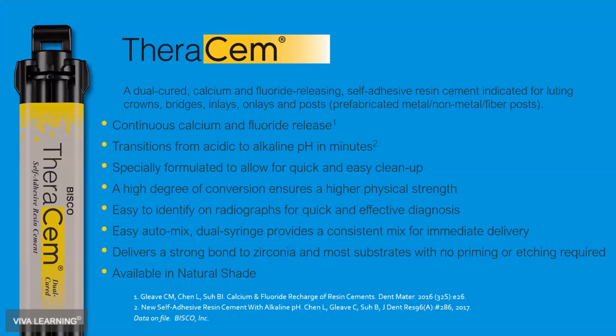And this whole generation, there is a chemical, which we'll talk about in a minute, which allows for most of this self-adhesion with little or no priming. Now, another unique feature of Theracem is that it transitions from acidic to alkaline in a few minutes, and we saw that way back with, remember, the zinc polycarboxylates. But that has a nice after effect for several reasons. One, a high pH will help to create even greater salting, if you will, at that junction. So your own minerals will help to further pack into any voids. But also, high pH does have an inherent antimicrobial feature to it.